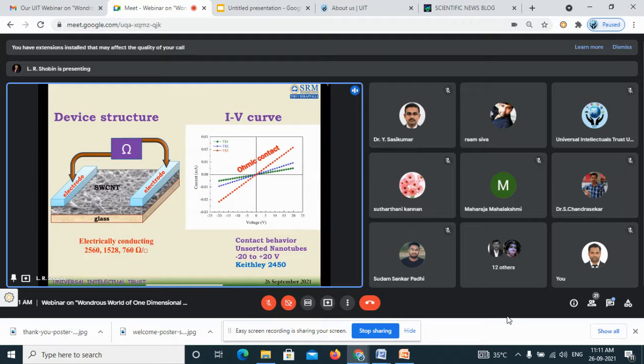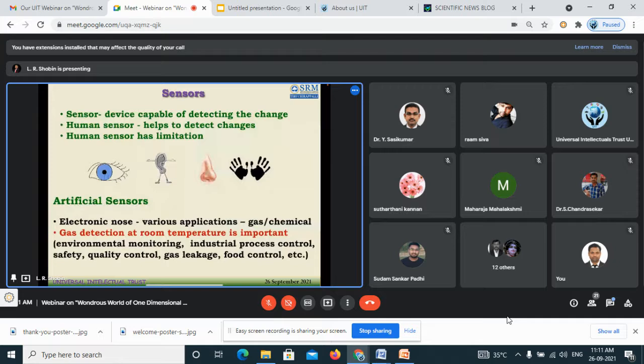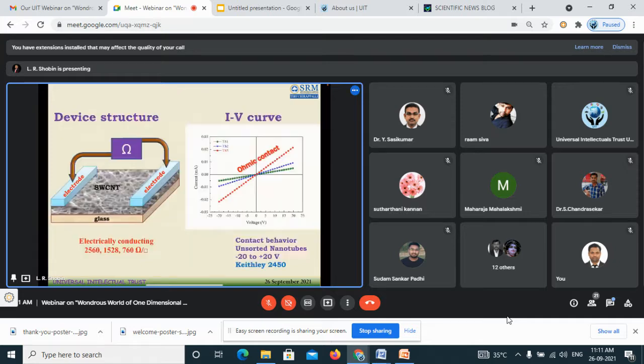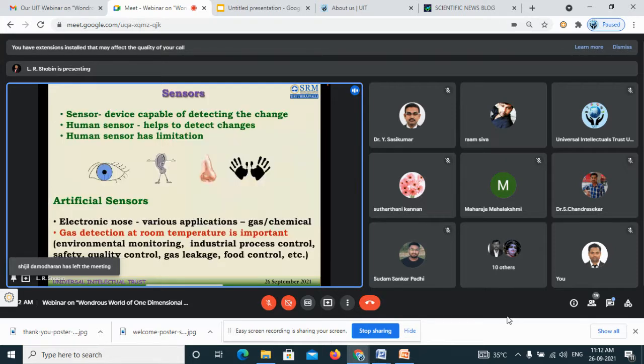Since the transparency is good but the film resistance is a little bit high, I cannot use it for solar cell applications. So what I have done, I use this film for sensors. I have used these transparent films for sensors. Since the resistance is high, I cannot go for the solar cells. So I have used this film for sensing.